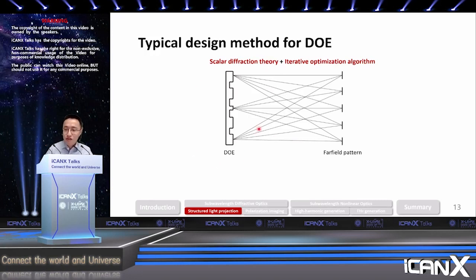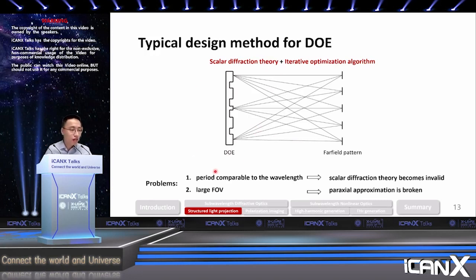But one of the problems we found in our case is that, first of all, since we are designing a metasurface structure with a period comparable to the wavelength of light, the effectiveness of scalar diffraction theory becomes quite questionable. Also, since we are designing a diffraction grating with a very large diffraction angle, or a very large field of view, some approximations, for example the paraxial approximation used in the Fraunhofer diffraction integral, get broken. So this entire method becomes invalid.